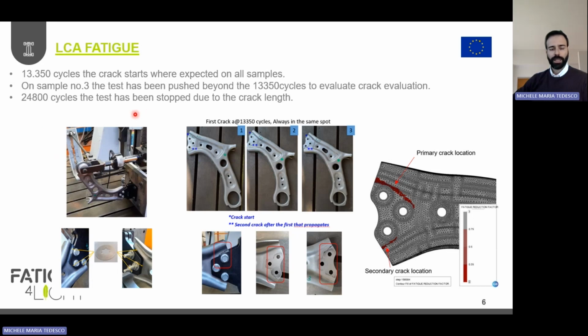On the sample number 3, we pushed the characterization over the 13,350 cycles in order to see how the crack propagation works on the component. And you can see here some images that correlate the cracks that we had in the real component, and also the cracks that we have in simulation, in which we define a first primary crack location here and a secondary one here.